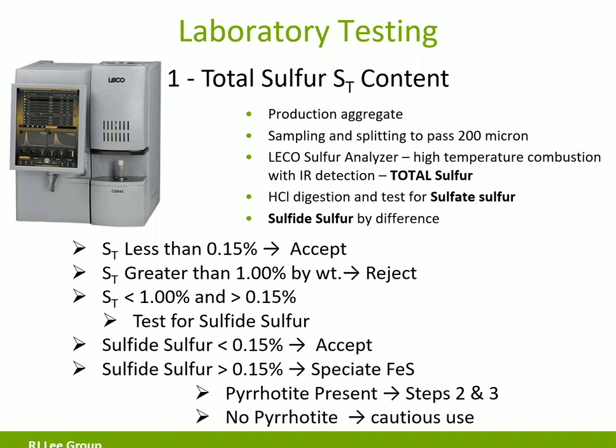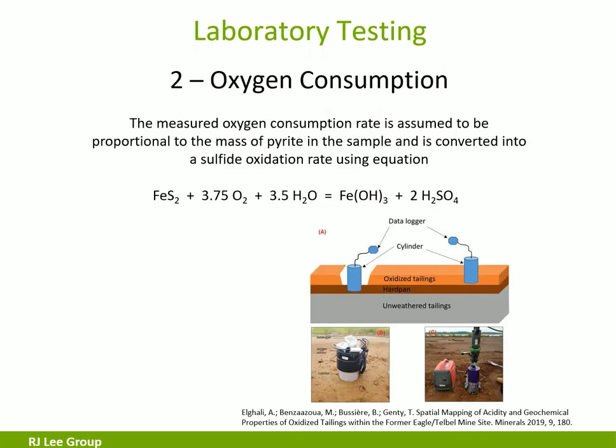So the first thing is the oxygen consumption test. I think that the limits they're using right now, if it's greater than 5%, you're going to go to step 3. And if it's less than 5%, you're okay. And the final step is mortar bar expansion, which has 2 parts to it. The first part is going to promote oxidation in order to determine expansion caused by the expansion products of the oxidation reaction. If you're above the level there, which is 0.1% after the 90 days, it could be ASR or iron sulfide. So you have to take a look at your mortar bar after that step. If you're at less than 0.10 after 90 days, then you're going to move to the second part, which is going to promote the secondary deleterious expansive minerals that form in the cement paste and cause the kind of damage you see in that image.